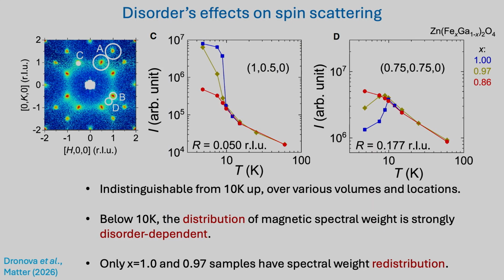However, after 10 Kelvin, you can see in the clean sample, when x equals 1, you have the Bragg peak rising rather quickly. However, in the interstitial part, you have this spectral weight reducing to lower values. The interesting thing is for the disorder sample, you don't have any redistributions, both on the 1.50 and 0.750, the spectral weight increases.